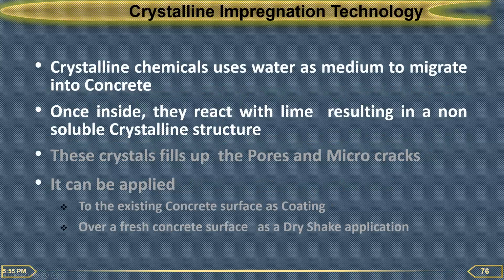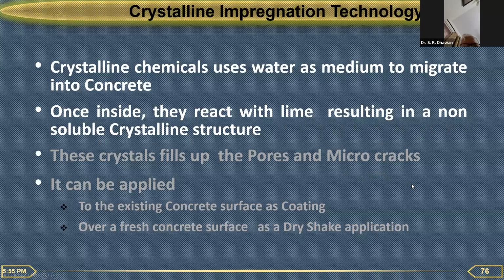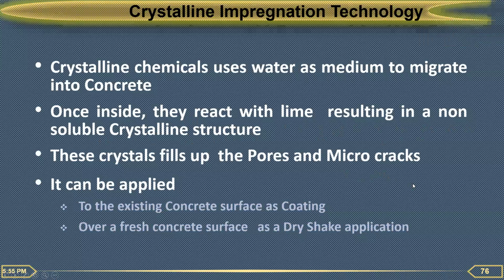Crystalline impregnation is also very important. We have seen how the crystalline technology is used as a material added to the concrete. Here, it can be used as an impregnation technology also. Crystalline chemicals use water as a medium to migrate into the concrete. Once inside the concrete, they react with the lime, calcium hydroxide, resulting in non-soluble crystalline structures, which I explained previously. These crystals will fill up pores and micro cracks. It can be applied to the existing concrete surface or over fresh concrete as a dry shake application.